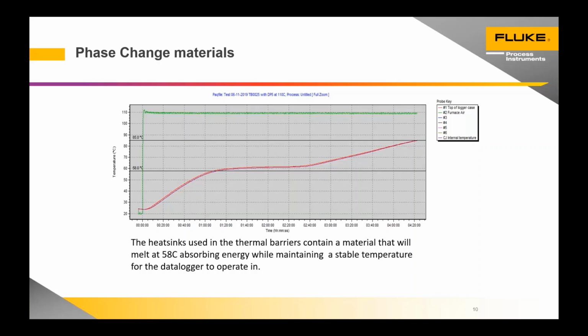But for the next hour and a half, the temperature of the data logger doesn't change. But you can see that all that heat is being absorbed into the melting of the phase change. After the 2-hour mark, the material has completely melted, and you see the temperature start to rise again. When we specify our thermal performances for all of the Datapack thermal barriers, it's specified at this point, at the end of the phase change melting, and that's what we give as the capacity. That gives us the safety margin on our specifications.